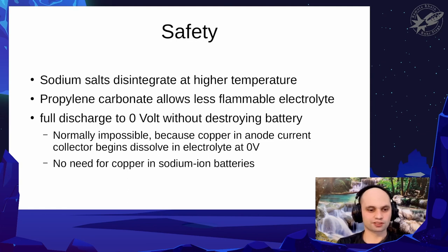increase the temperature of the battery even a little bit more, and a little bit more, and a little bit more, and at some point you reach the point where the cathode material itself starts to disintegrate and release oxygen or some other volatile components, and the entire thing starts to heat up and essentially combust. That's a big problem with the NMC materials, nickel manganese cobalt for lithium ion batteries, which can be very flammable. It's much less a problem with other materials.